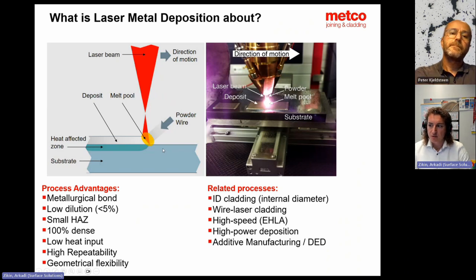You can go in further with monitoring and temperature measurement. I can even measure temperature within this, let's say, spot. Then I can introduce a filler material in terms of powder or wire to this area. And then I build a melting bath, which interacts with my substrate material in a very minimum way. So it means we extremely reduce heat affected zones, we have less impact on substrate, and we also minimize distortion while still maintaining a metallurgical bonding. So the biggest advantage of welding is a metallurgical bonding.